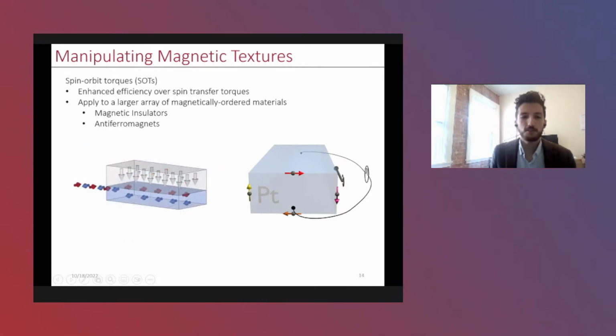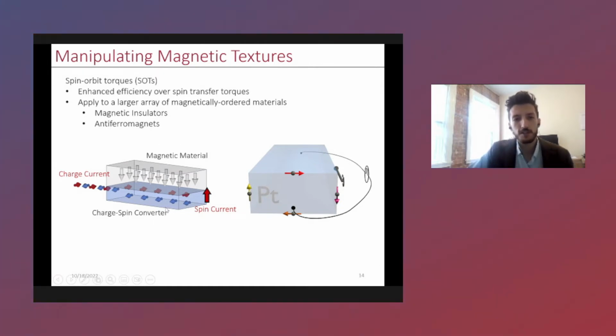So essentially, if you place one of these materials, these charge-to-spin converters, next to a magnetic system, you can actually take this charge current and drive a torque into the magnetic material. And the beauty of this is not only its efficiency, but you can actually apply this sort of spin-orbit torque to a larger array of materials. So things like magnetic insulators, which we'll look at today, and antiferromagnets, which we'll also look at in today's talk. And this has been demonstrated. We've known this, of course, for over a decade. It's been used to both drive domain walls and switch the magnetization of different types of magnetic materials.